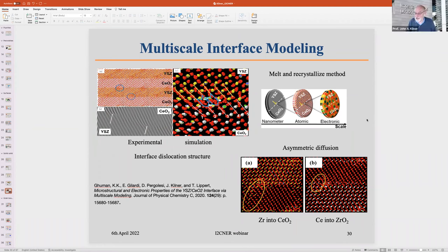Yeah, a very good question again. Let me see if I can answer it. I think the answer to both questions is that the perovskite acts as a sink. The perovskite is known as the chemical chameleon. You can fit virtually any ion in the periodic table on either the B or the A site. So it has the ability to accommodate a very large range of ions. And I think that has been the saving grace for the fuel cell, because otherwise the surfaces of these perovskites would be covered in impurities.